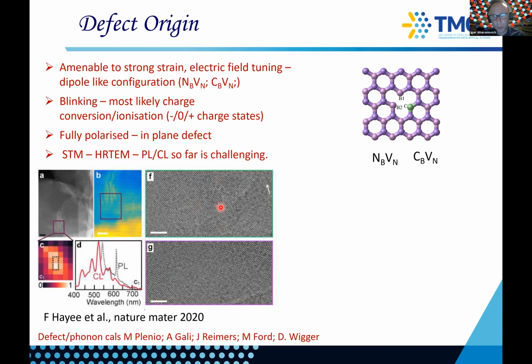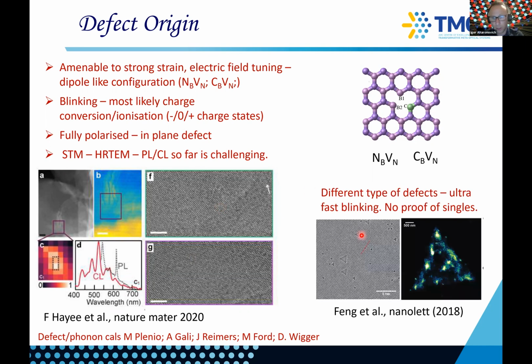And so the other approach was, well, let's try super resolution imaging. And here, this is work from Igor Aharonovich's group at UTS. And so what they did is they took a very well-defined triangular flake, and they imaged it down to about 10 nanometer resolution. And then they took the same flake into a scanning electron microscope. And again, within 10 nanometers, you would have quite a few defects. So this correlation, although hBN really offers an outstanding platform to correlate between TEM, STM, and super resolution imaging, it is still hard to really go down to the single photon level.